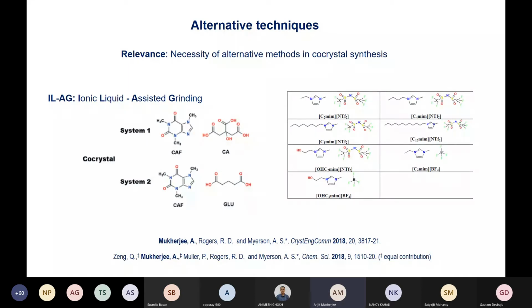So there is always a necessity to extend this, because then we can manipulate and design co-crystals according to our needs. In this context, I have mentioned the POLAG, polymer assisted grinding technique, which was introduced by the William Jones group a few years ago. There they mentioned that ethylene glycol polymers, depending on the chain lengths, can be used in co-crystal formation. This work was done in Professor Myerson's group. What we thought here is that ionic liquid also can be used for the same purpose.